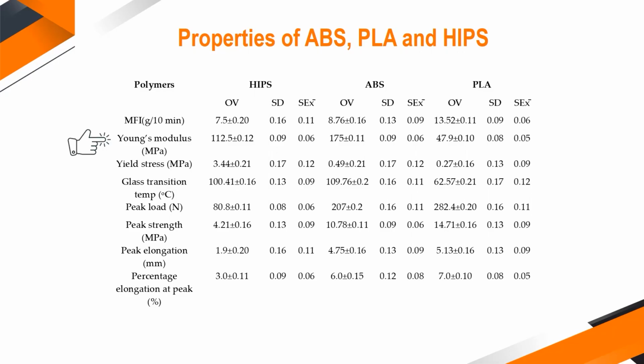Then for ABS it was 8.7, for PLA it was 13.52. So you can see there is a significant difference in flow properties. That means the thin section that I am interested to make is how significantly different for these three polymers. Then you can see there is a difference in their Young's modulus, like 112, 175, 47. Similarly, other properties like yield stress, glass transition, peak load, peak strength, elongation, there is a significant difference.